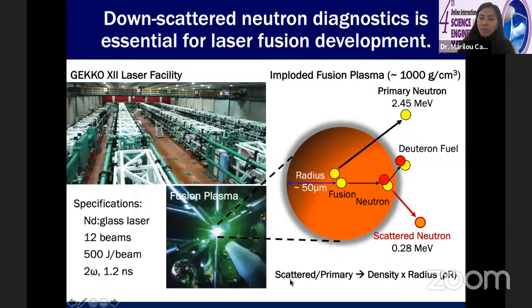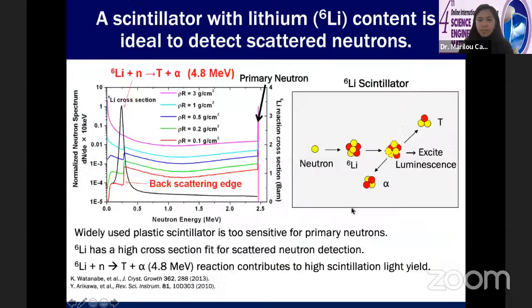The ratio between the scattered and the primary neutrons is proportional to the density of the fusion plasma that's generated. So it's thought that if we wanted to control laser fusion, we should be able to control the density of the fusion plasma. And therefore, it's very important to be able to measure the ratio of these scattered neutrons and primary neutrons in the fusion plasma that's generated. But that's not so easy.